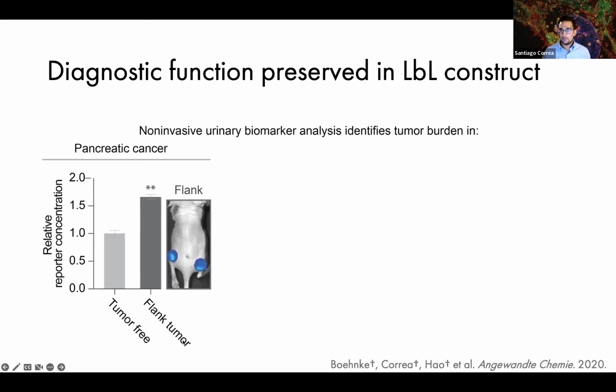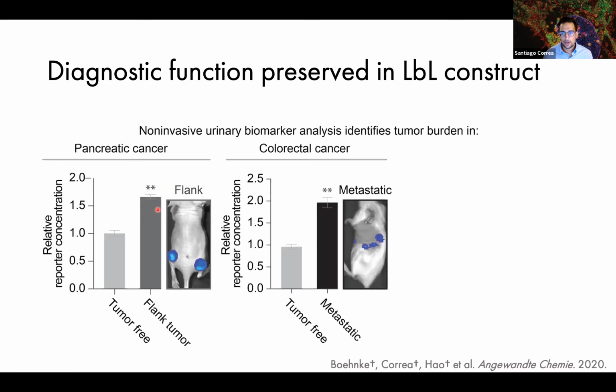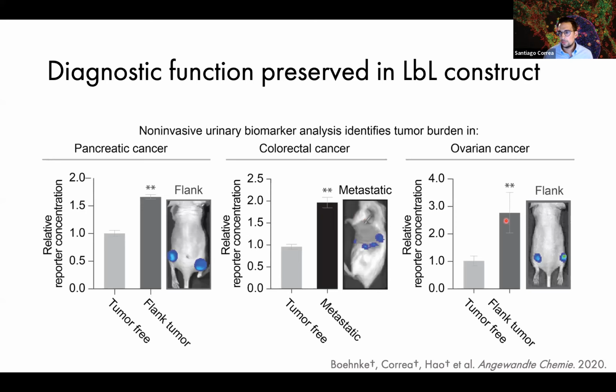And so for that, we turned to in vivo studies, looking at a number of different tumor models. What we do here is inject tumor-bearing or tumor-free mice with our nanoparticle, and then collect the urine 2 hours later and see how much of that protease, or the protease-sensitive peptide, I should say, we can detect in the urine. Our first test was with a flank model of pancreatic cancer, and what we saw was this very clear elevated signal in the urine of tumor-bearing mice. We saw a similar result in a metastatic model of colorectal cancer and in a flank model of ovarian cancer. And so overall, we were pretty pleased and convinced that we had preserved the diagnostic functionality in our hybrid nanoparticles.